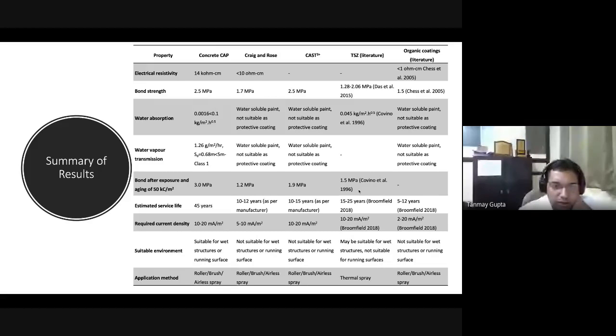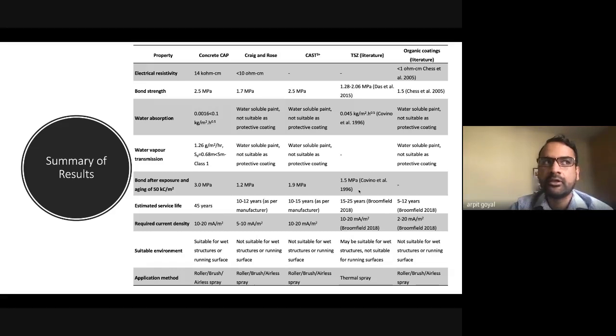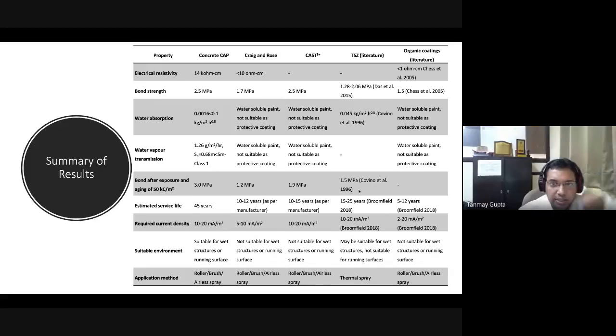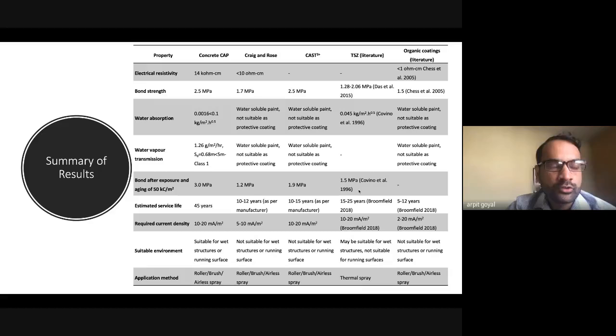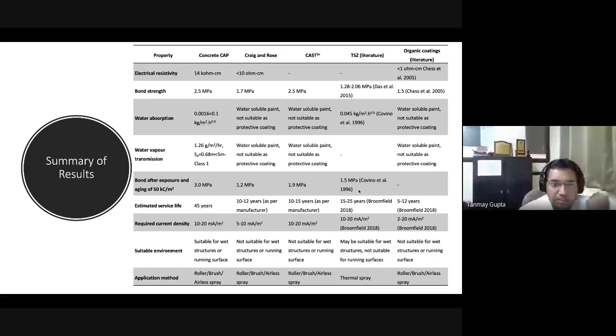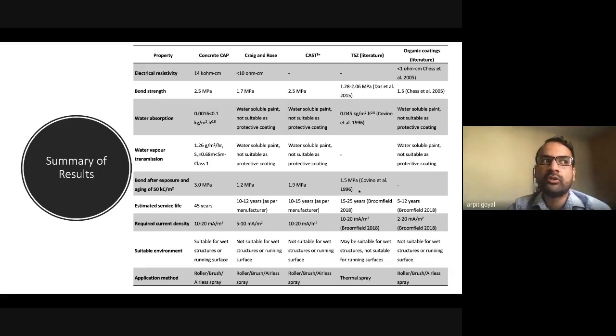Okay. And you have estimated 30 to 45 years of service life. Yes, 30 to 45 years of service life. And is there some criteria which you have applied? Sorry? The estimated service life, is it based on some empirical results? No, we actually did some accelerated tests in the laboratory for estimating the service life.